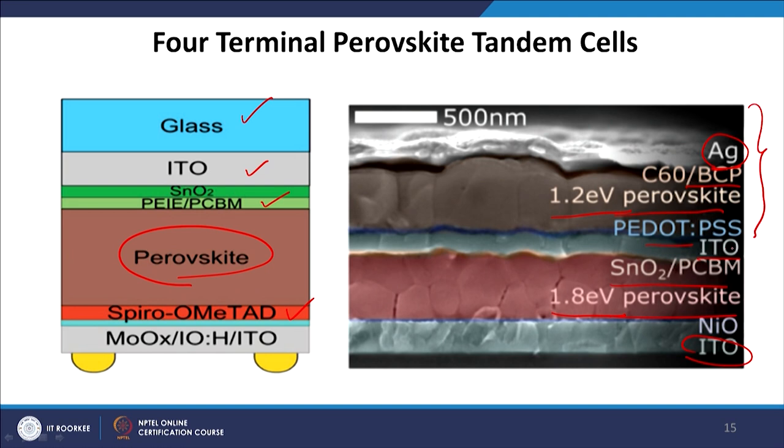So, we have an ITO layer and then PEDOT:PSS, right, then the perovskite which has a band gap of 1.2 electron volt, then C60 and the BCP, and then the Ag layer. So, that is a PIN geometry of a perovskite solar cell. Now, you look at the bottom layer here, ITO and then nickel oxide, then 1.8 electron volt perovskite, then SnO2